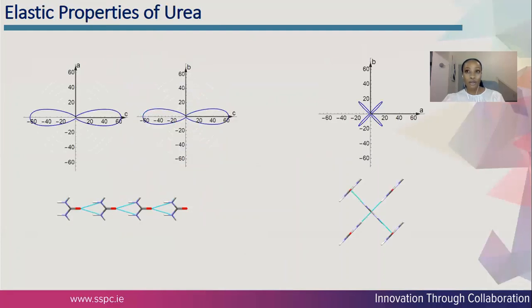The result is that urea looks the same in two orthogonal directions, which are the AC and BC planes. That also means that urea shows the same mechanical behavior in the AC and BC planes, as shown by the 2D spatial dependence of Young's modulus. The largest resistance of the Young's modulus is in the C direction, and it coincides with the infinite tapes of urea extending in this direction. On the right, from the AB plane, the cross-like arrangement of the NHO hydrogen bonds is reflected by the cross-like shape of the Young's modulus. More so, the stiffest direction of the Young's modulus in all three planes corresponds to the direction of the hydrogen bonds, suggesting that the hydrogen bonds confer extended strength to the Young's modulus.